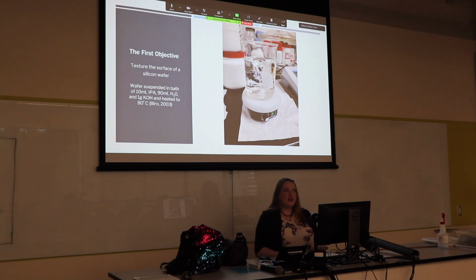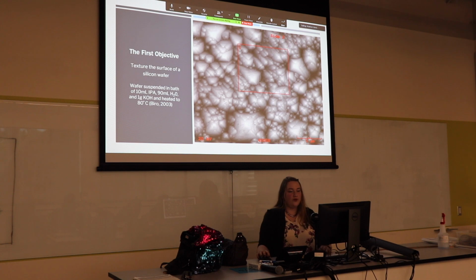Before the sample went in, it had a very flat, almost spongy looking texture with lots of plateaus, and afterwards we can see these beautiful pyramidal structures, which in theory the light goes in, hits off one of the sides, gets reflected onto another pyramidal structure, and might bounce around a couple times before leaving the cell, which increases the efficiency.